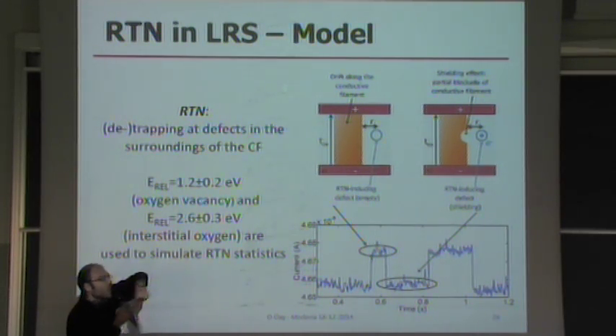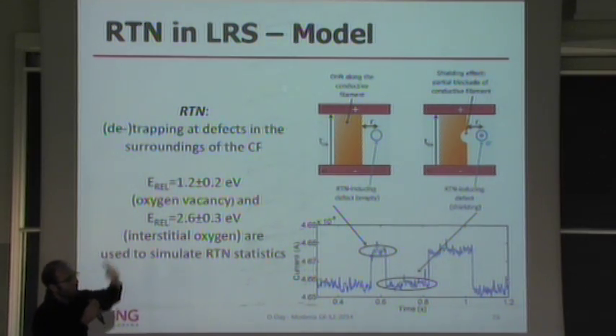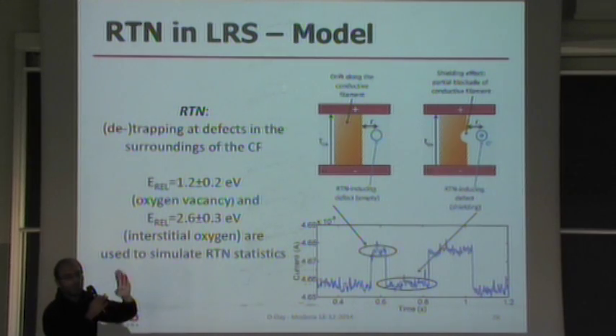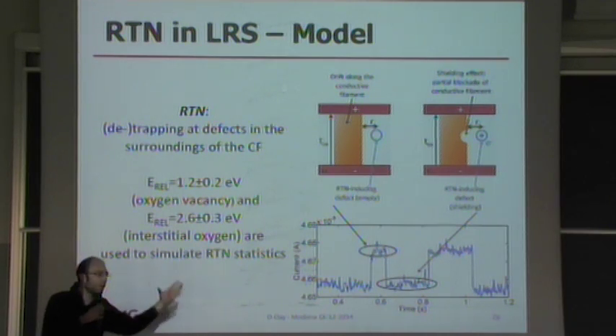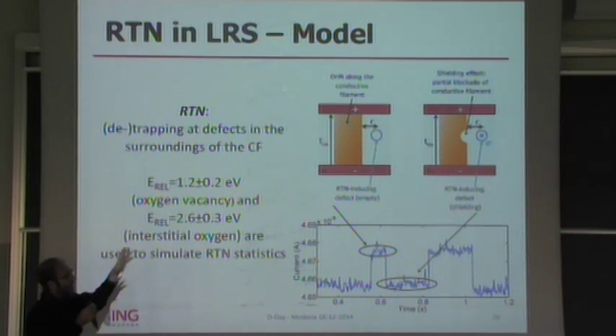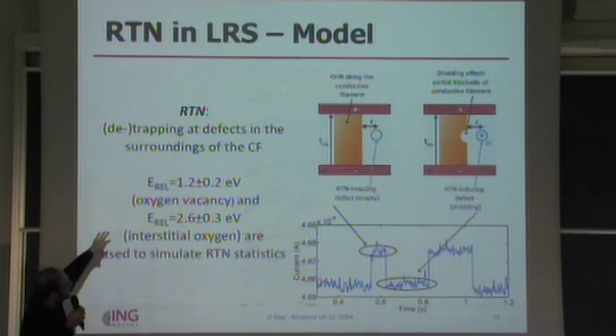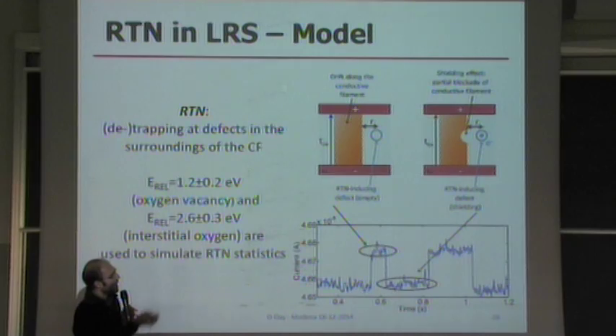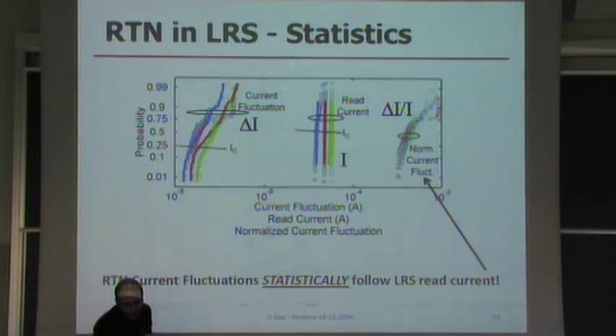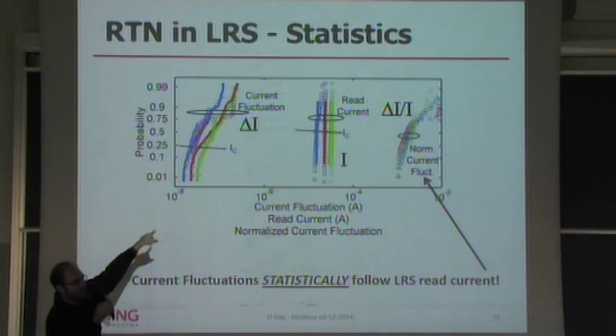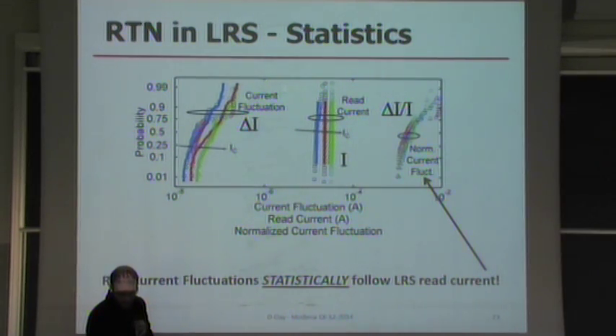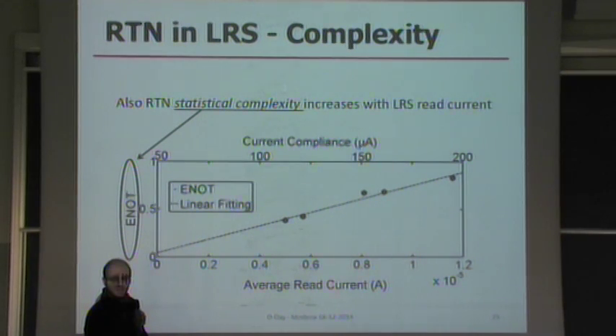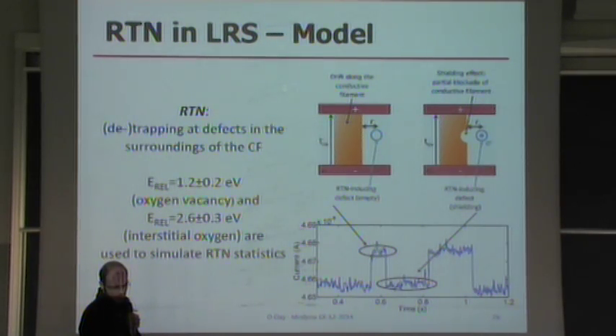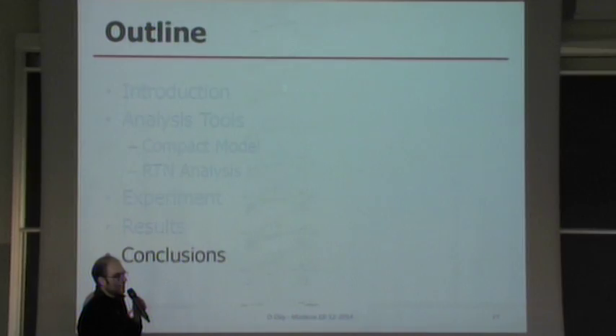But it is surrounded by defects, and the charge trapping and detrapping at these defect sites may induce a kind of screening of the walls of the conductive filament and may cause RTN fluctuation in a very similar way to HRS, but now the defects are located elsewhere. But it seems to us that the defects are exactly the same. Oxygen vacancies and interstitial oxygen are used to simulate these dynamics, and actually we have this nice matching between lines and symbols, simulations and experiments. So it seems that the models we proposed can really explain the very nature of RTN, and it paves the way to the incorporation of these effects in the compact model.